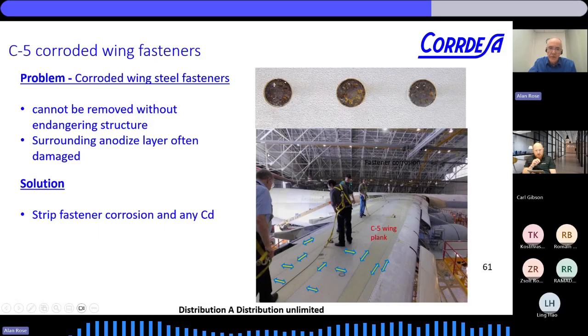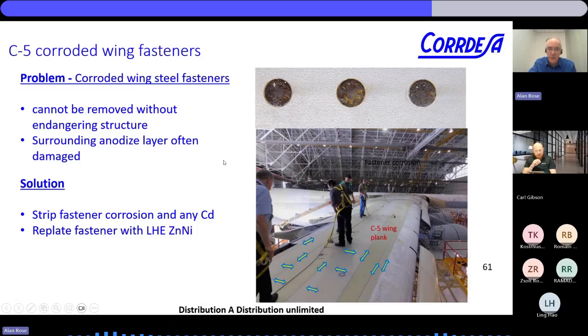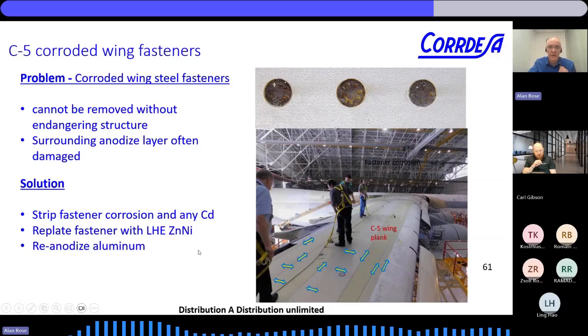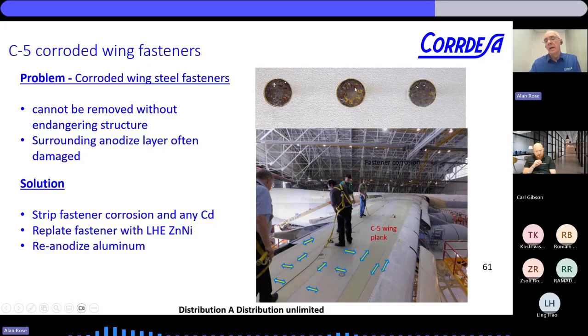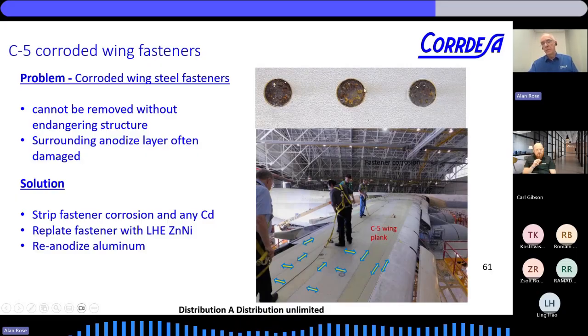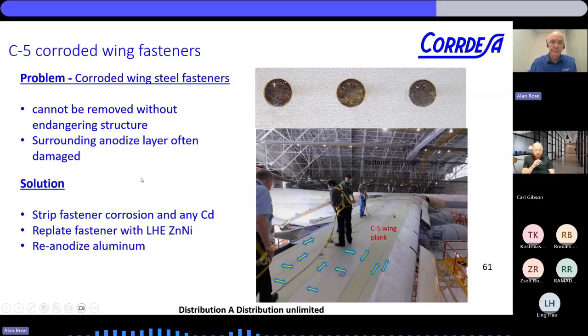Anyway, so what we did then was it was similar to that U2, but we've got larger tools. So you can see the corroded fasteners here. We've stripped the cadmium off there. If there's any left, it's often completely gone by then. We can't coat with cadmium. It's possible to do it, but of course, low hydrogen embrittlement zinc nickel is now what we're replacing it with. And then reanodize the aluminum, because what they found is that in removing the corrosion, the technicians essentially were putting abrasion material on the end of drill bits and damaging the actual plane as well.